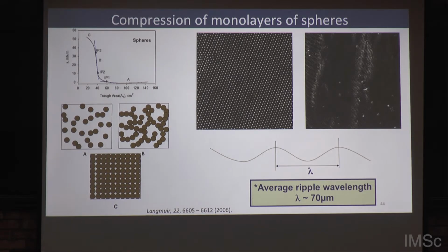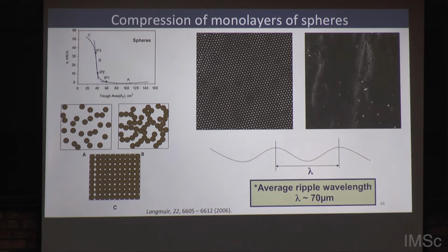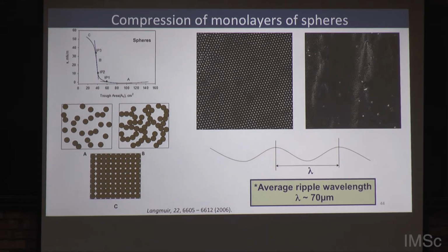when you do these experiments, what you do is you put in a dispersion of particles and a little bit of an alcohol, because alcohol acts as a spreading agent. During the initial stages of compression, alcohol is still evaporating, and we know that the presence of a small amount of alcohol reduces surface tension. I would say that, no, this is for sure,